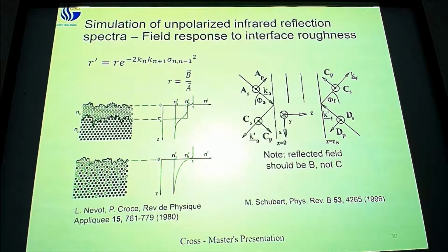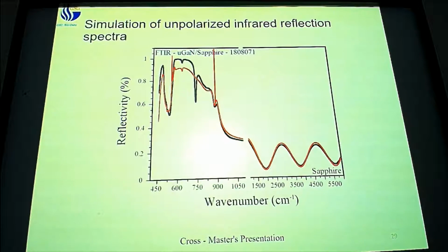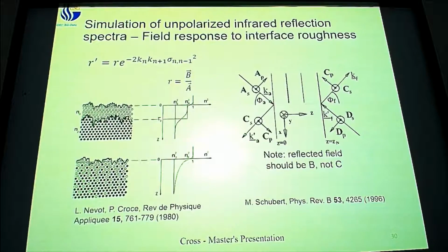Can you relate that? So long wavelengths here, I think these are actually the long wavelengths here. At the short wavelengths, it seems to work pretty well. Yeah, reciprocal space, sorry. Yes. So here it's working pretty well because we're not very rough. I'm going to put it bluntly: we don't have a particularly rough surface at this point, which is great for gallium nitride, but for indium nitride that is a problem, and we'll see that in a second. So the roughness is what I'm hoping to incorporate into this model as well.